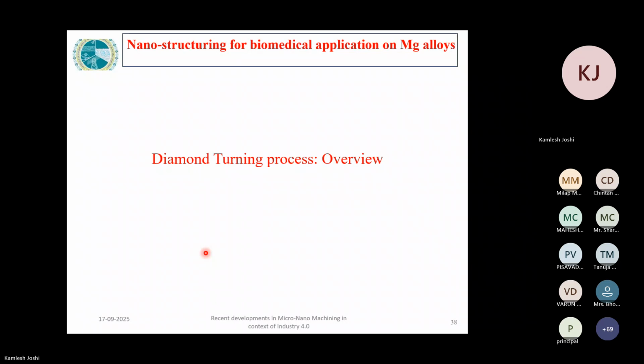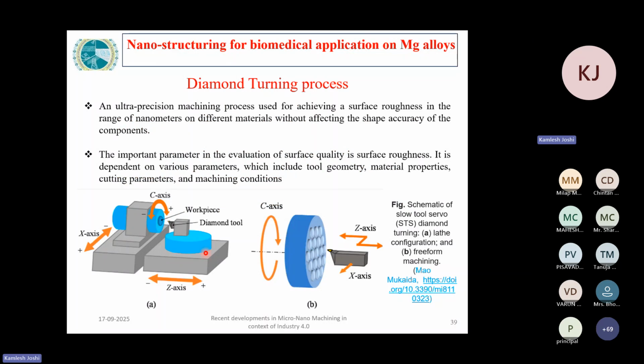So first we'll see what this diamond turning process is. The diamond turning process is similar to our conventional lathe machining process. The only thing is that the tool size is very controlled, and it is an ultra precision machining process which is used for achieving a surface roughness in the range of nanometers on various difficult to machine materials without affecting the accuracy of the components. The famous material used in the diamond turning process is aluminum. Brittle materials like silicon carbide are also usually investigated with this diamond turning process.